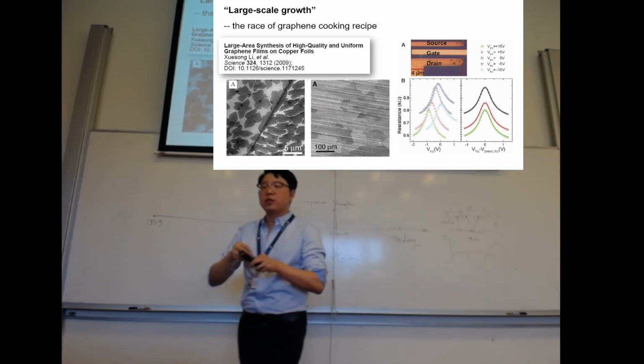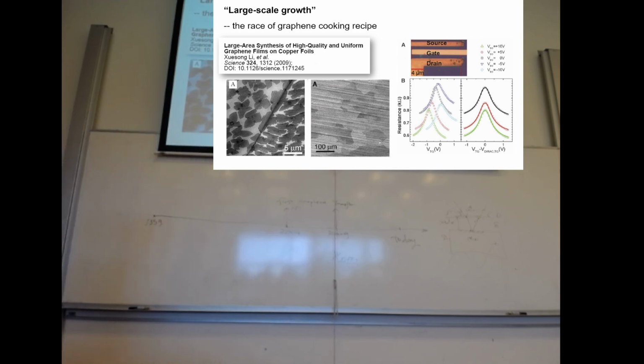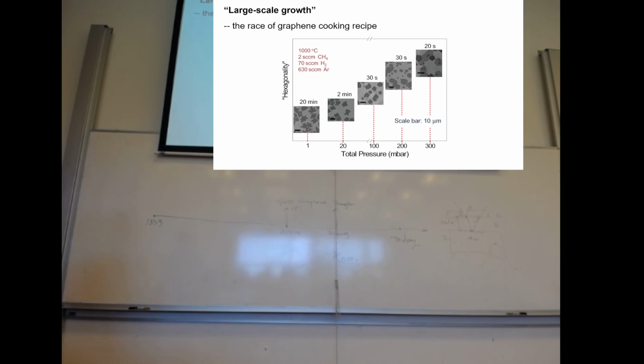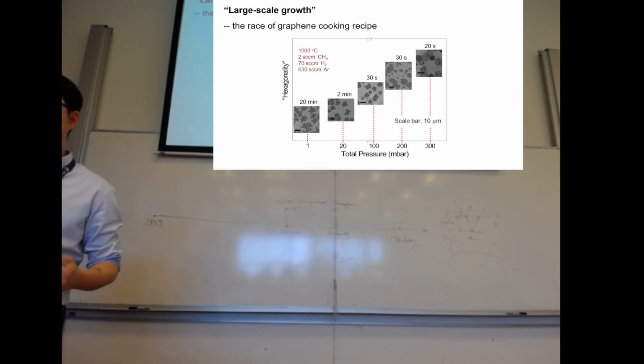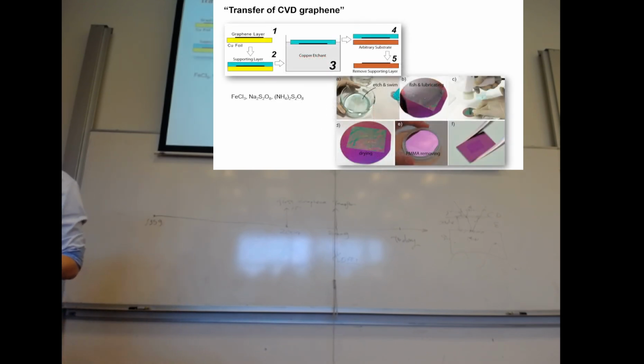And you can do a lot of transport experiments, anything you can imagine. So maybe you have already noticed that the graphene flakes, when you do CVD growth, have different shapes. They have flower-like, hexagonal shapes, and sometimes irregular shapes. That is purely dependent on the thermodynamics of CVD growth. By tuning the partial pressure of different gases, you will get different shapes of graphene. That's already a well-known phenomenon. So this is how people transfer graphene from a metallic surface to an arbitrary surface, let's